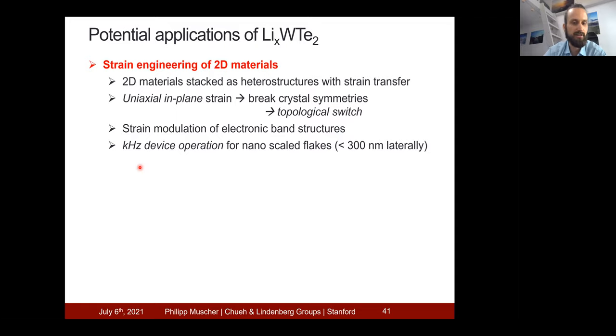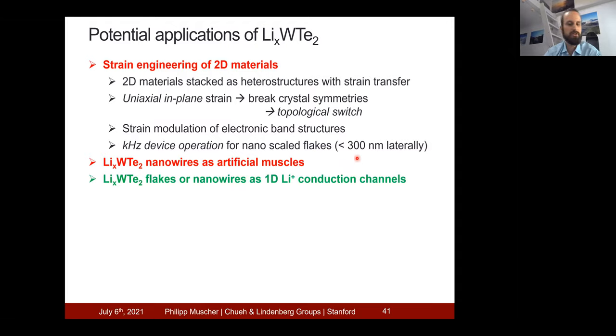And that type of tuning could be done at kilohertz device operation if only the tungsten ditelluride flake is scaled in a way that's smaller than 300 nanometers laterally. This comes from the fast diffusion coefficient in the system. Also in the field of actuation, we could use tungsten ditelluride nanowires as artificial muscles. We could also use tungsten ditelluride flakes or nanowires as one-dimensional lithium conduction channels due to the fast transport properties in this A-axis in-plane direction.